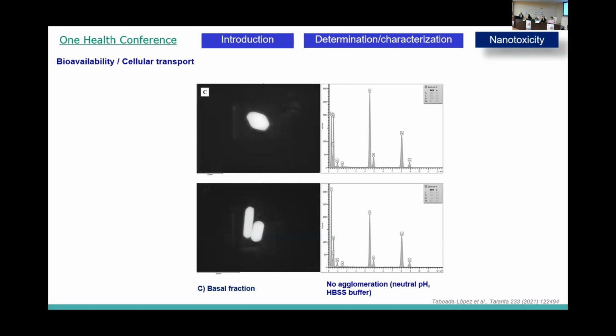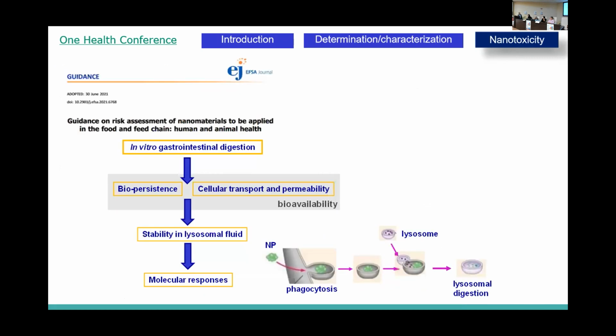So regarding the possible dissolution of the nanoparticles during the procedure, we cannot be sure, because in addition to this phenomenon, we have to take into account the agglomeration and dispersion phenomena, because nanoparticles depend on the environment. So it's quite difficult to say that during the transport there is a dissolution or ionization of this type of materials.